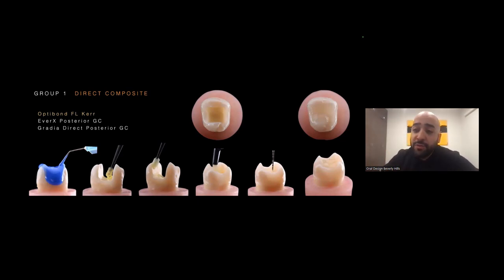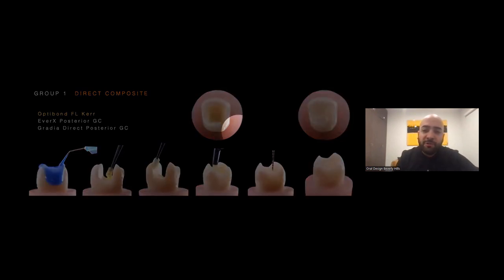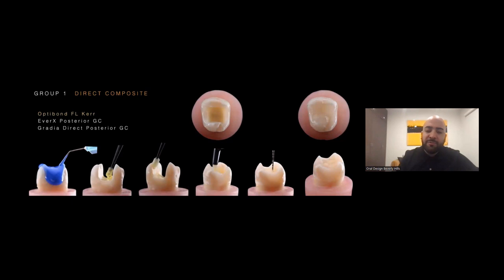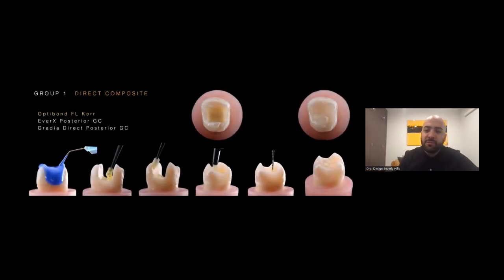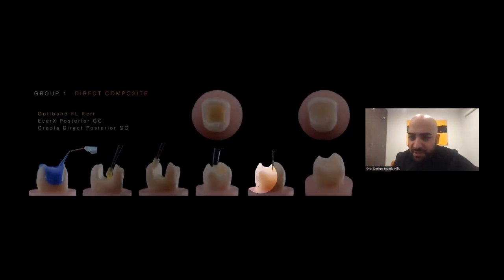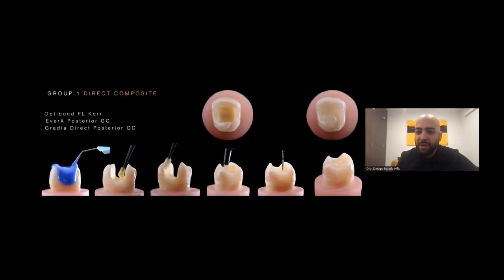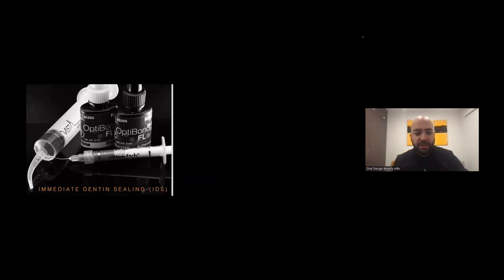Something very important to know about fiber reinforced composite is that this material is not designed to be exposed to the oral environment. That's why for all these samples, we build our proximal walls so that we are taken into a class 1 situation. Then we fill up the bulk of our cavity with fiber reinforced composite. We leave 2 millimeters on the top, and then we finish it up with a regular direct composite restoration.